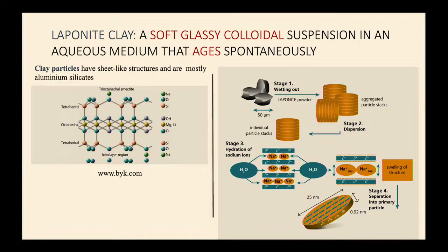And this is why the aging happens, because there's this evolution of the microscopic structure of the clay. There are these tactoids that are swelling, and particles that are falling off. Now remember, each particle has an anisotropic distribution of charges. It's a disc like this, with the faces negatively charged and the rim positively charged, which depends on pH. In the experiments that I'll be telling you about, this is exactly what they look like. These things can be controlled, so it's a fantastic test bed to do all kinds of experiments.